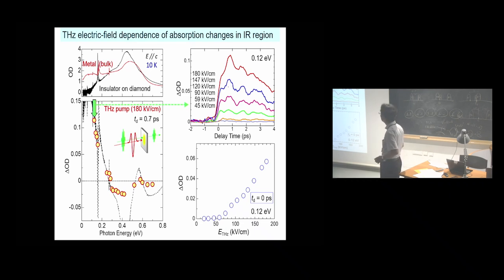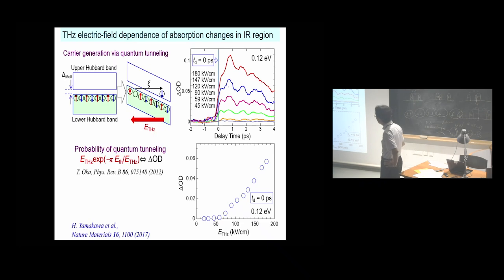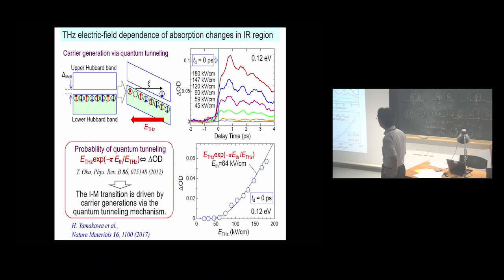To clarify the transition mechanism, we next investigated the electric field dependence. This figure shows time evolutions of the absorption changes for various electric field amplitudes at 0.12 eV, which can be a measure of the carrier density. This is the electric field dependence of delta OD at 0 picosecond, this point. This shows threshold behavior. The theory predicted that the probability of quantum tunneling processes can be expressed by this exponential formula. The result is well reproduced by this formula. This demonstrates that the insulator metal transition is driven by carrier generation via the quantum tunneling mechanism.